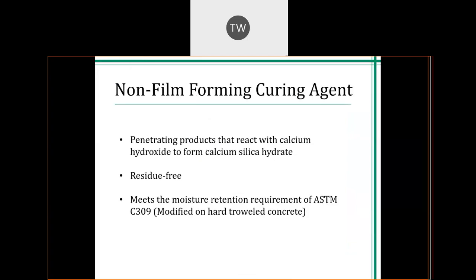So a new trend in the concrete industry is non-film forming curing agents. It meets the moisture retention requirements of ASTM C309 on hard troweled concrete, but it does not meet the full ASTM C309 specification because it is not a film forming cure. It is a penetrating product that is going to react with the calcium hydroxide to form a calcium silicate hydrate reaction. So this would actually be a great application for a warehouse floor or even a second story slab that has already been installed.